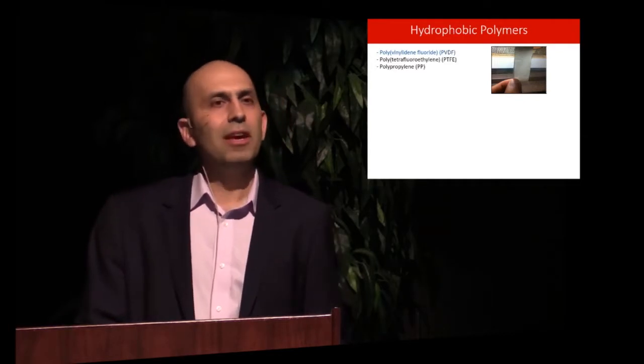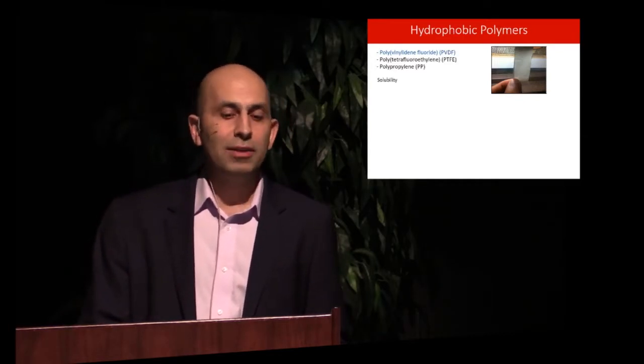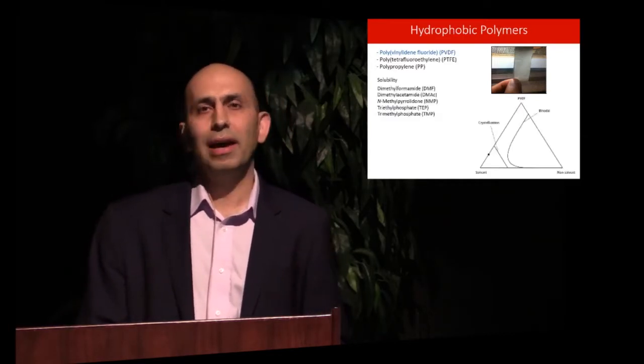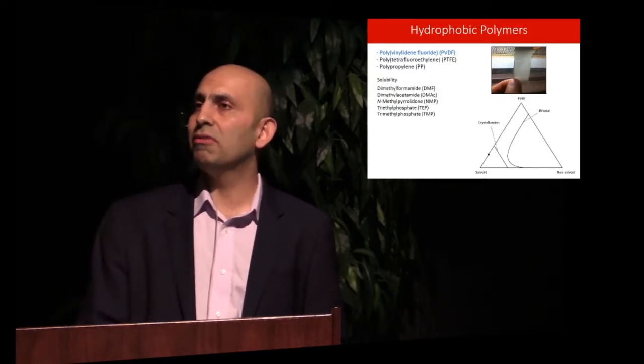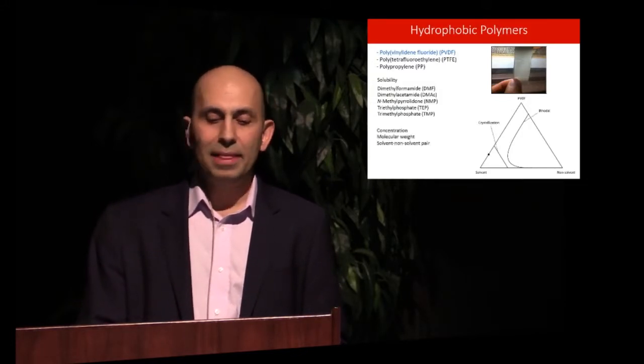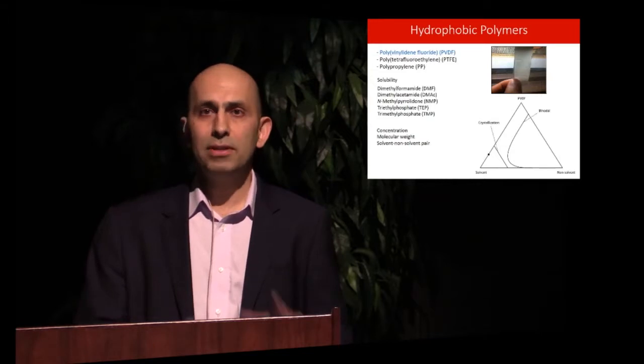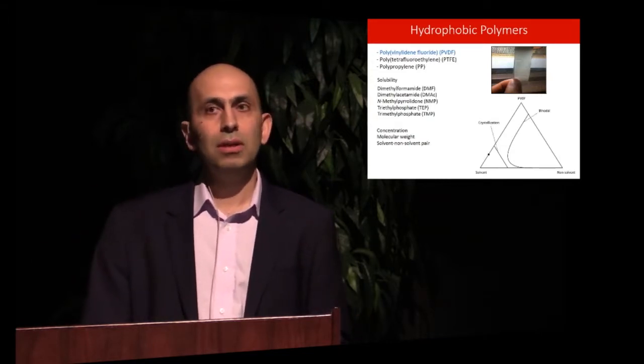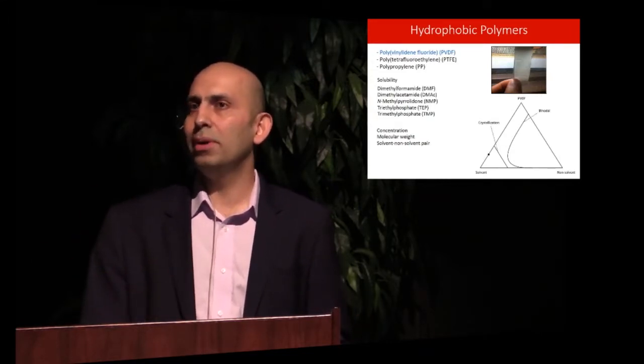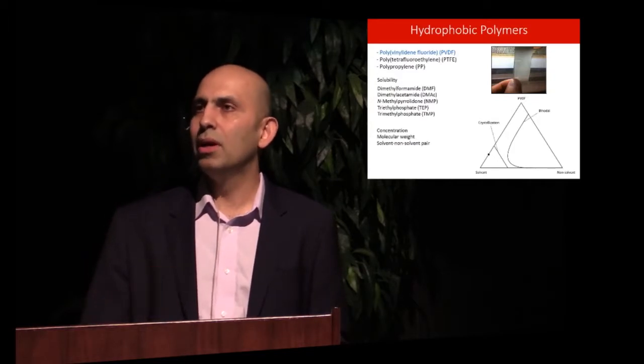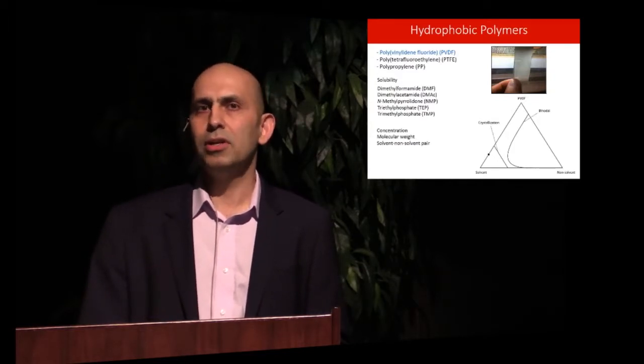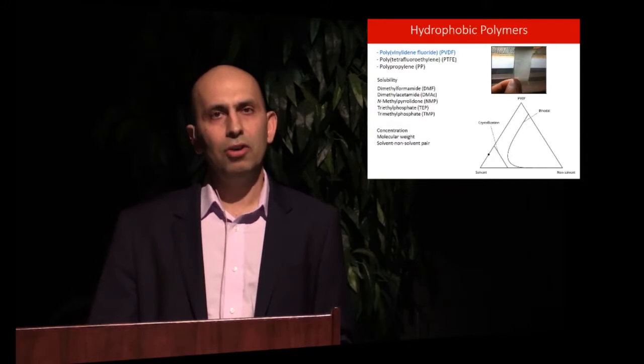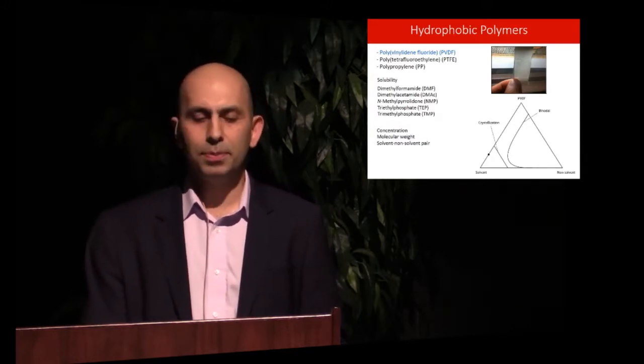So we chose PVDF, or polyvinylidene fluoride, and we looked at different solvents, and it turns out that it can dissolve in many different solvents. And then we started navigating through the space of these parameters to see if we can find the proper configuration or proper operating condition for making a hydrophobic membrane suitable for the MD process.